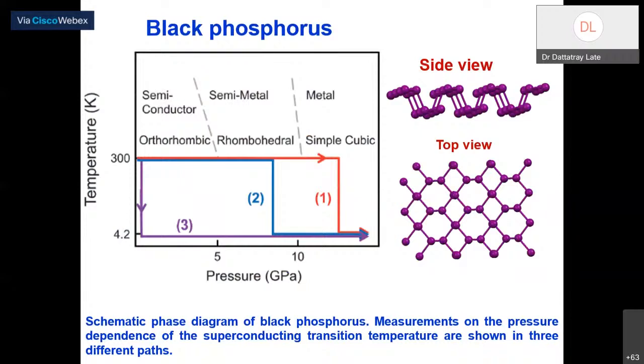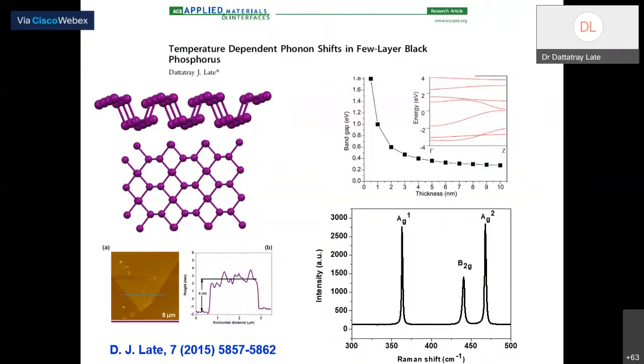Okay, so these are just the phase diagram. When you pressurize the material, you can convert this semiconductor into a metal phase. Of course, you can choose the structure, orthorhombic or rhombohedral or just simple cubic, just by pressurizing the material. Okay, so this is the schematic structure. We have done a lot of experiments like temperature dependent Raman spectroscopy of this few layer and multi-layer black phosphorus.